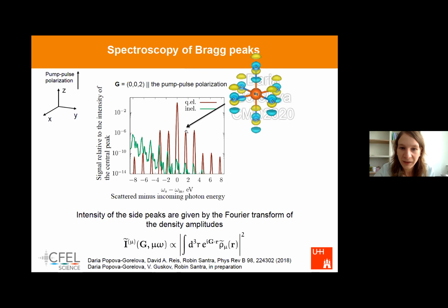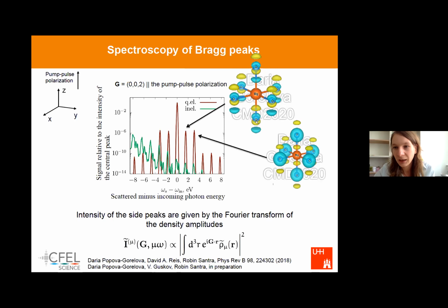And we could prove that this first order side peak is the corresponding Fourier transform of this charge distribution. Then the second order side peak is the Fourier transform of a second order charge distribution. Magnesium oxide is a crystal with inversion symmetry, and in principle it doesn't have second order macroscopic polarization. But what we found is that it indeed has second order microscopic polarization, as shown here. So charges still rearrange within the unit cell, but it doesn't have any dipole moment. That means that you cannot measure this response macroscopically. But with this method, with X-rays, you get access to this second order response, and that gives rise to this second order side peak to the main Bragg peak.